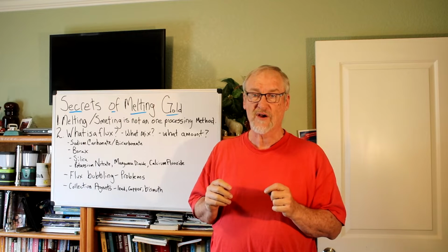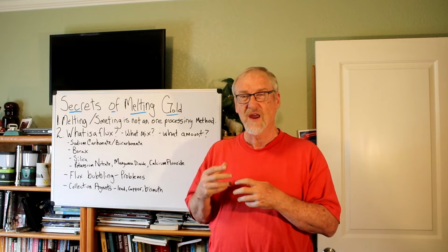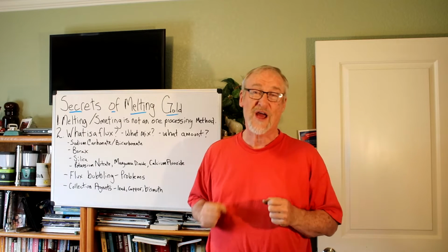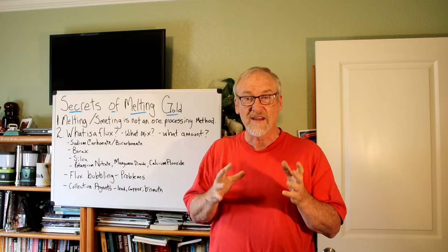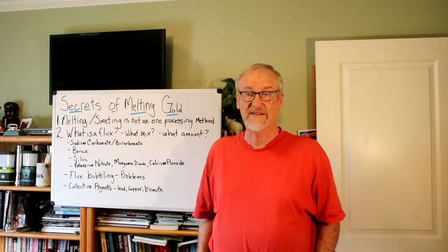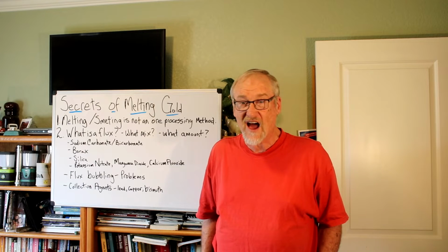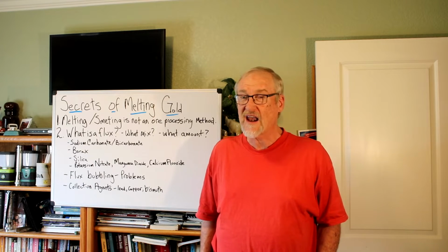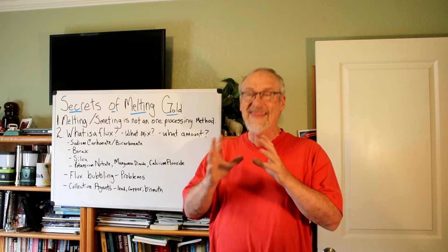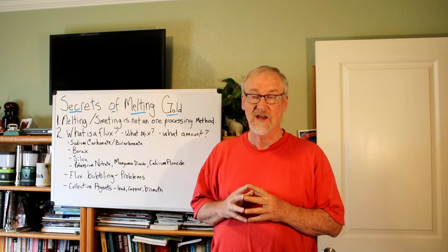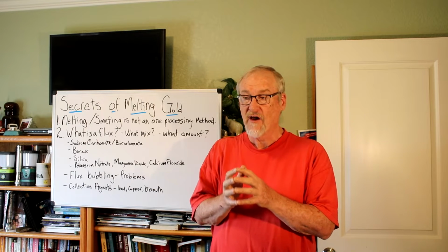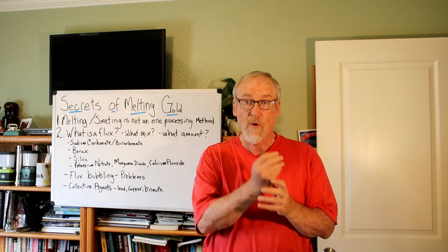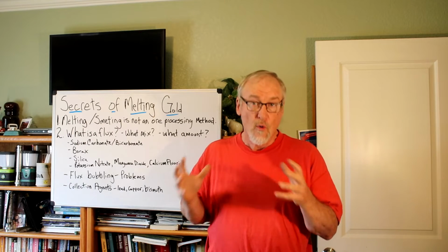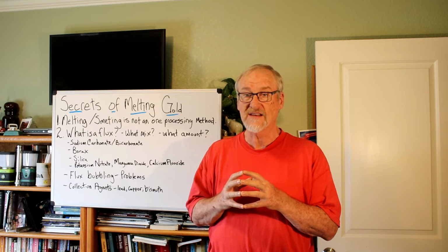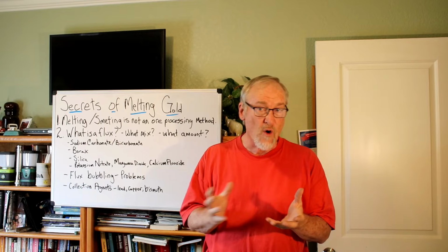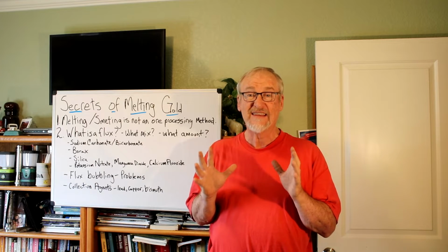But the other impurities that are often with gold, especially if I'm going to melt some gold and show you guys in a minute, a lot of that stuff is dry wash concentrates. And there's little bits of iron oxide and pyrite and probably a little tiny bit of quartz in there too. And that's the stuff that gets absorbed into the flux. So when I melt that stuff, the iron oxides will go into the flux, the quartz, the silica will go into the flux, any kinds of other black sands go into the flux, that sort of thing. That's not a metal, right?